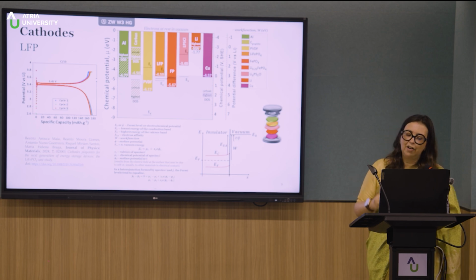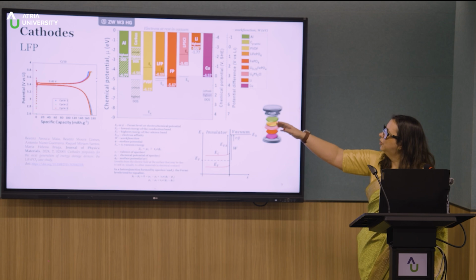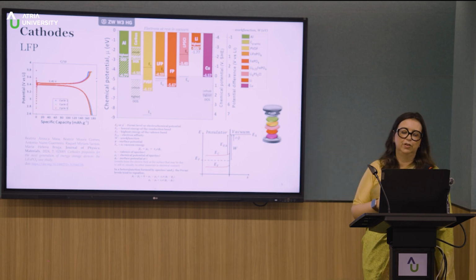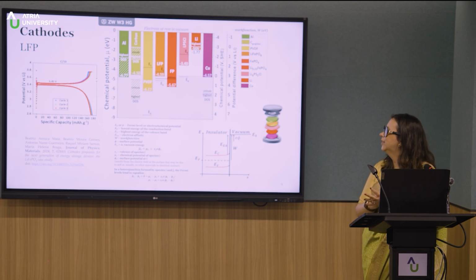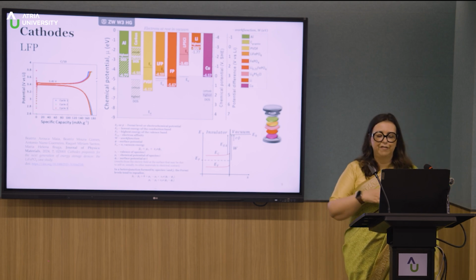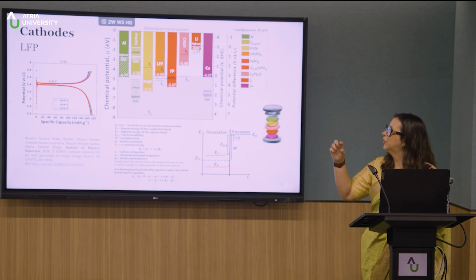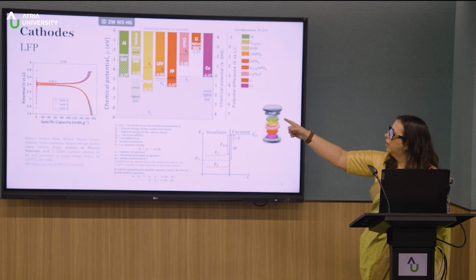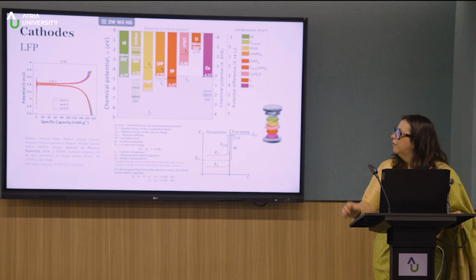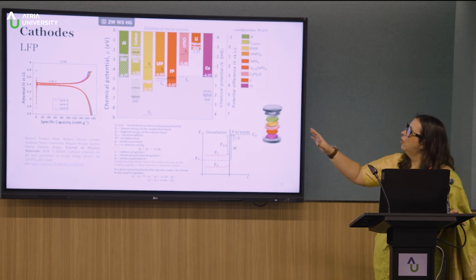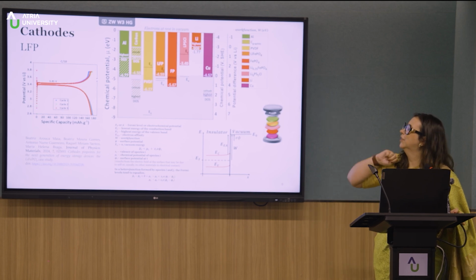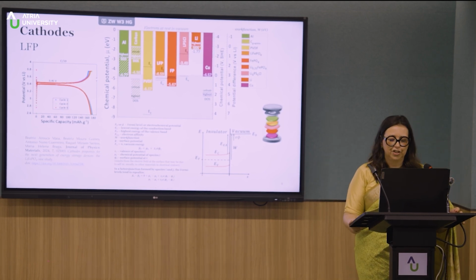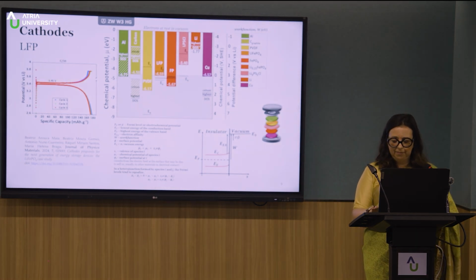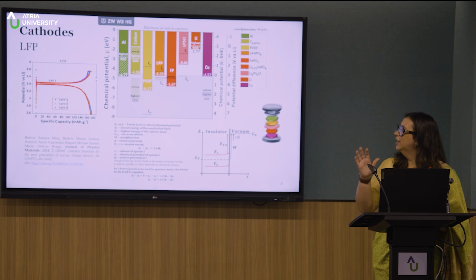Also, from the calculation, the simulation, we can predict what will be the theoretical plateau energy. And with all this knowledge, with all these numbers, we can see if we are very far away, if we have a huge resistance, because if we have a huge resistance, we will not see the equilibrium at 3.45, and we can actually know what is the cutoff voltage for charging and the cutoff voltage for discharging. So it's very important to understand the materials. This is the message, and to understand especially the electrical properties of the materials.